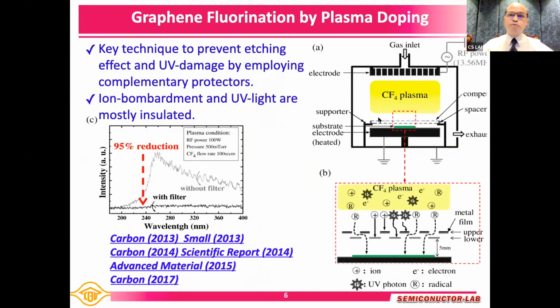And our approach is just using the plasma dopings. So I introduced you earlier. We just using the filter try to filter the UV irradiations because we want to just perform the fluorine doping. So we just introduce CF4 plasma, CF4 gas. And during the plasma, UV irradiation will damage the 2D material very much. So that's why we're using the filter here. And we just check the UV irradiation will be much reduced. Almost 95% of the UV irradiation will be reduced.